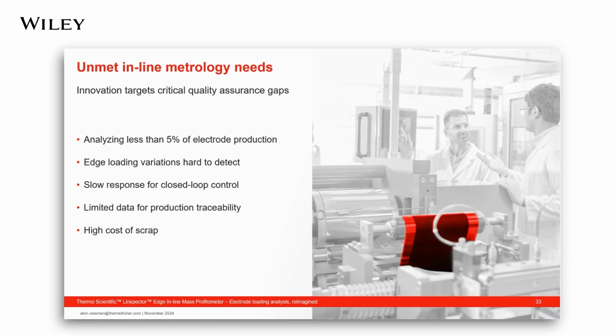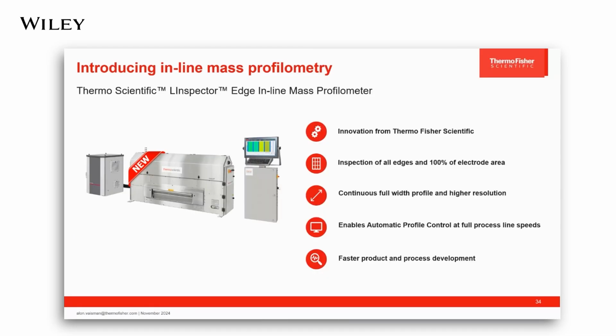Conventional single-point sensors only interact with a small fraction of the surface of the electrode, usually less than 5%. Variations in loading on the edges of the coating are difficult to measure, and the time it takes to collect data for representing a loading profile is measured in multiple seconds, slowing down the ability to respond to process changes. Data available for traceability and failure analysis is also limited to the same small fraction of the product, resulting in potentially non-conforming areas of the electrode making it into the downstream process and resulting in costly scrap of a complete cell. A new technology introduced by Thermo Fisher earlier this year aims to address these challenges.